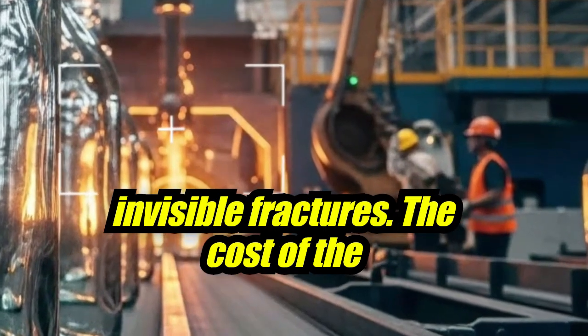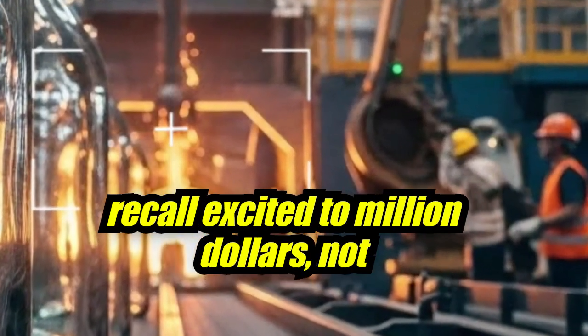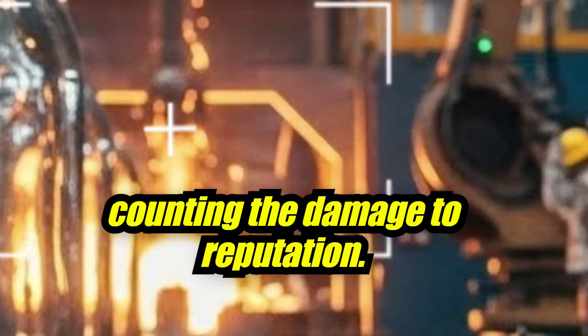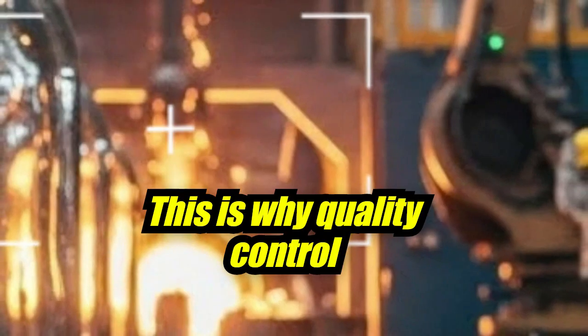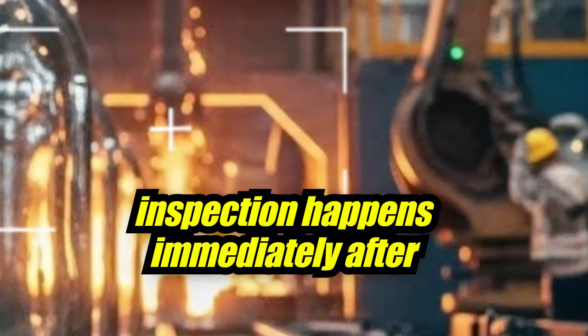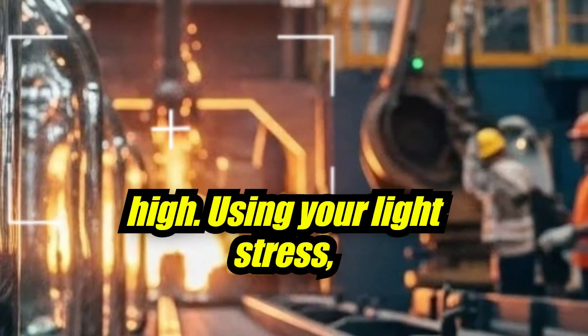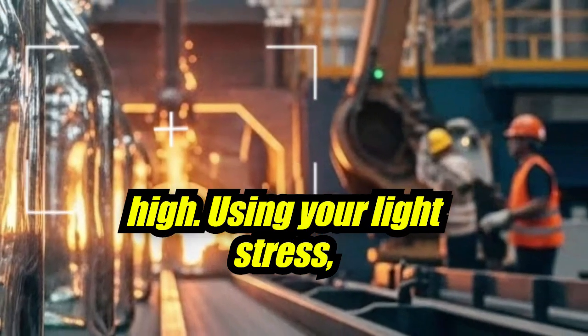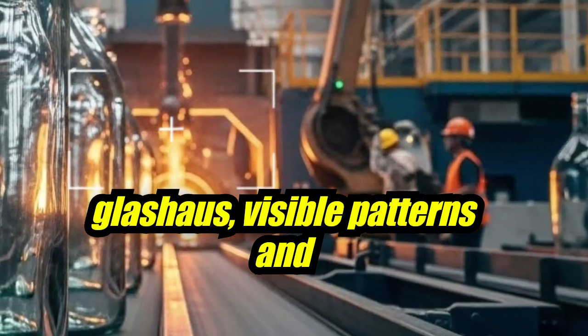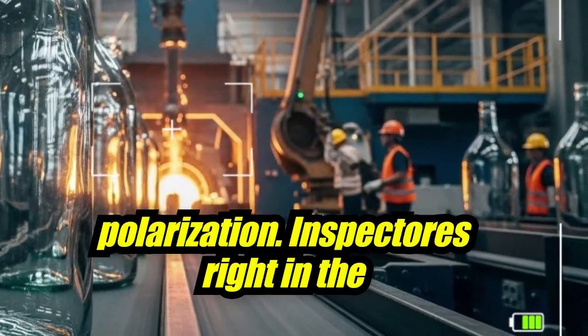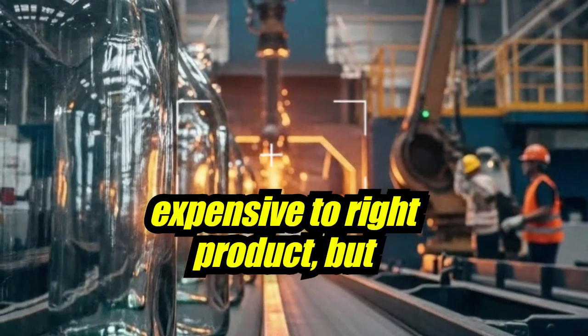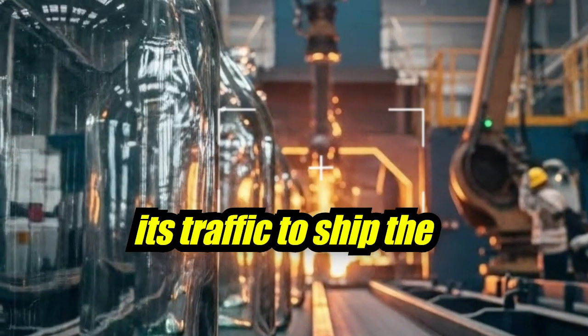The internal stress from improper annealing had created invisible fractures. The cost of the recall exceeded $2 million, not counting the damage to reputation. This is why quality control inspection happens immediately after annealing using polarized light. Stress glass shows visible patterns under polarization. Inspectors reject entire batches if defects exceed 2%. It's expensive to reject product, but it's catastrophic to ship defective product.